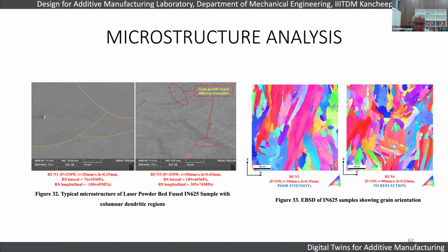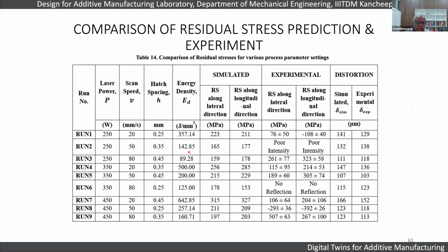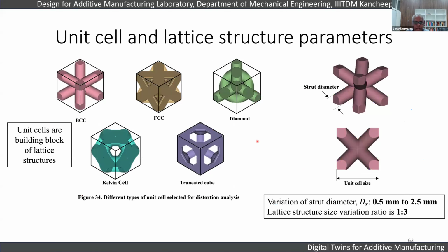But when you use very high energy densities, we get comparable results, and you can see that somewhere you get a compressive stress, sometimes you get a tensile stress, because there are positive and negative values. So with all these learnings, we chose the one software which gives us a lot of confidence in terms of comparable results with the experimental results. We selected that data as the data for training the AI. So we used those simulations.